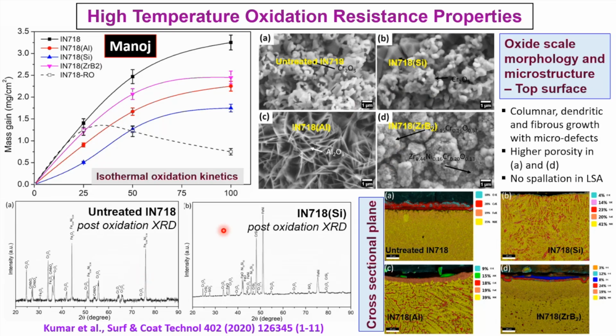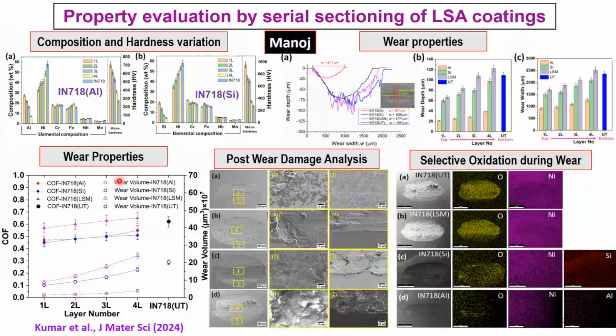What is really interesting here is that if you look carefully, you'll see a number of intermetallic phases still remaining with large peaks on the surface despite 100 hours of oxidation, which proves that even after 100 hours, you don't have the surface entirely covered by oxides. You still have these intermetallic phases which are preventing further oxidation, so they're very effective in preventing it.